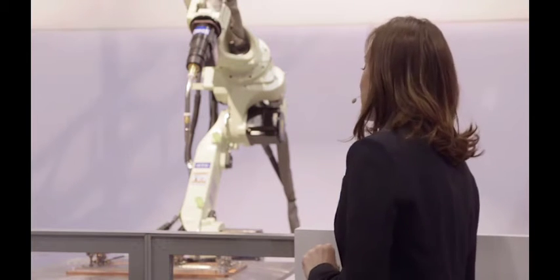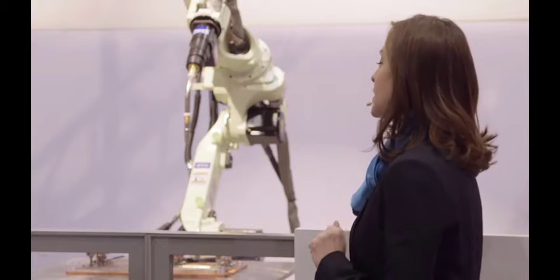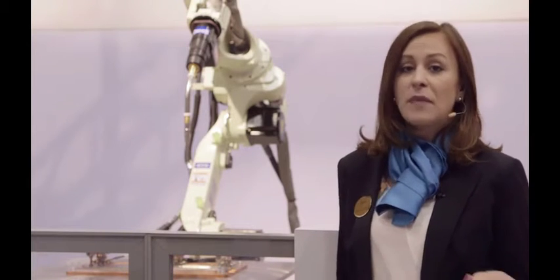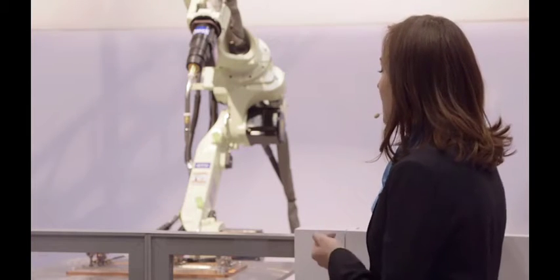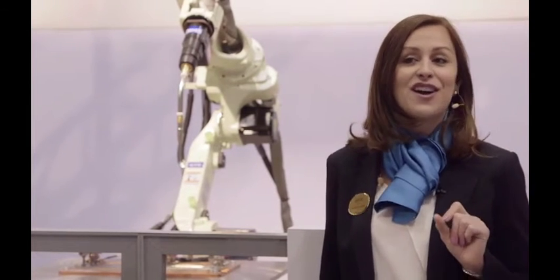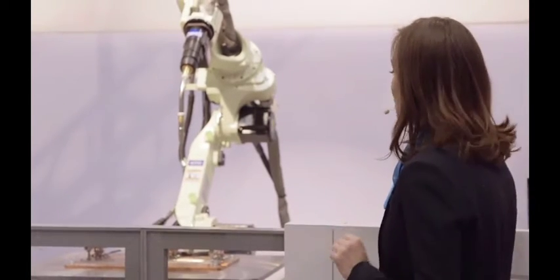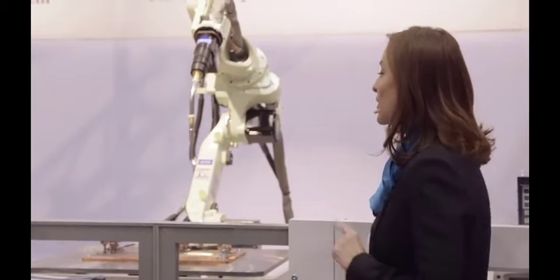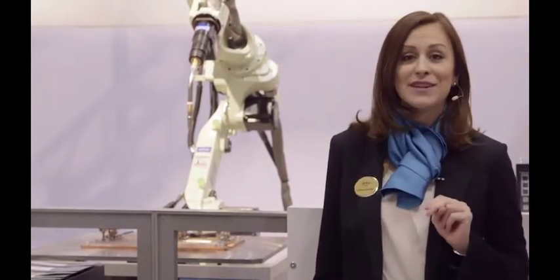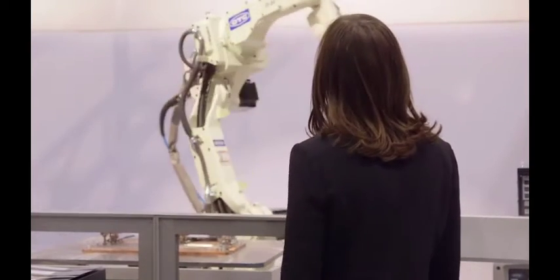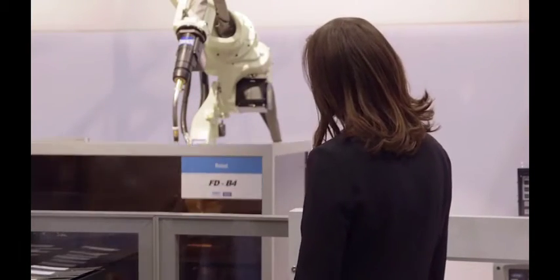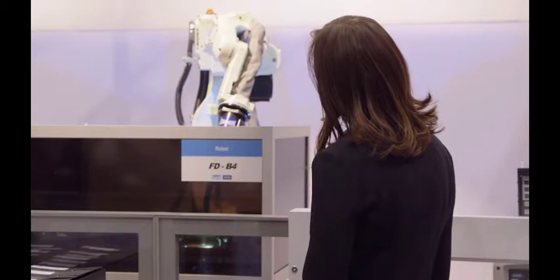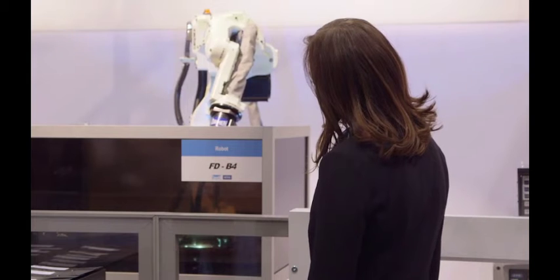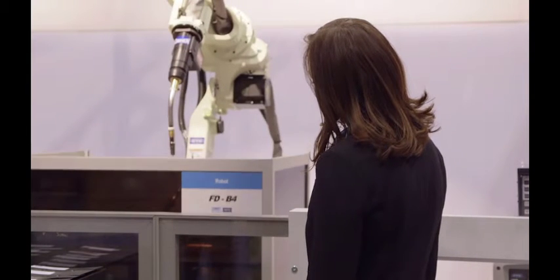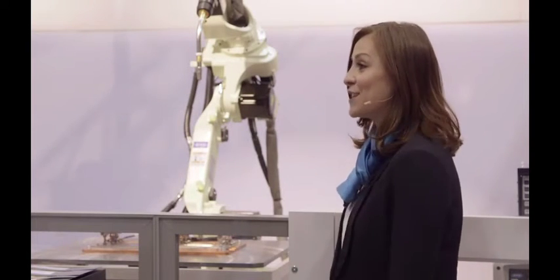In the first demonstration, 0.6 millimeter ultra thin mild steel plate is lap welded, common to automotive body welds and the like. The wire diameter is 0.045 inch, the welding current is 60 amps, and the travel speed is 20 inches per minute. We're using 80% argon and 20% CO2 shielding gas. You can see that almost no spatter is generated and stable welding is achieved.